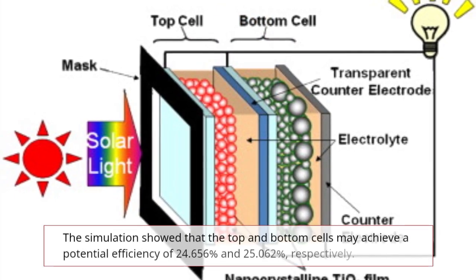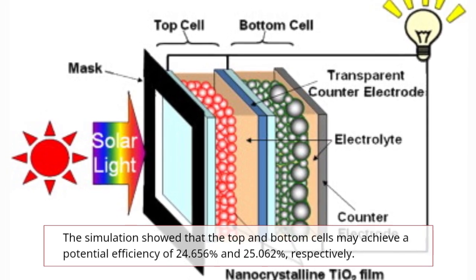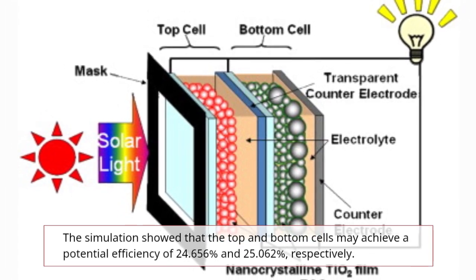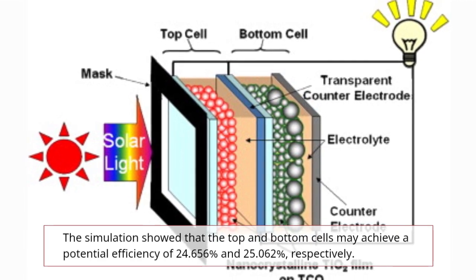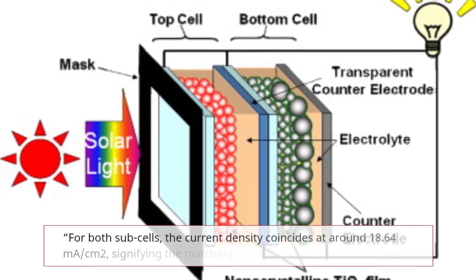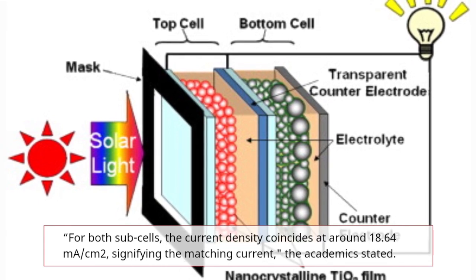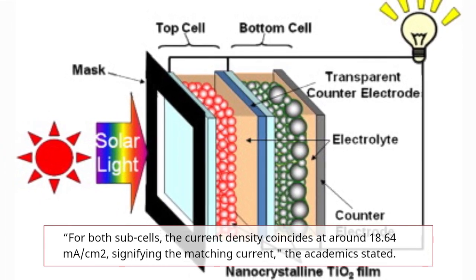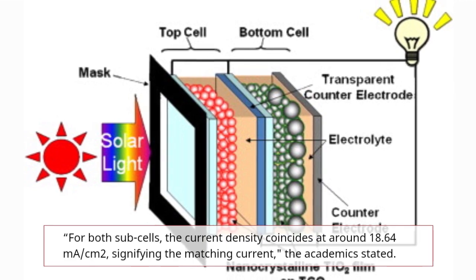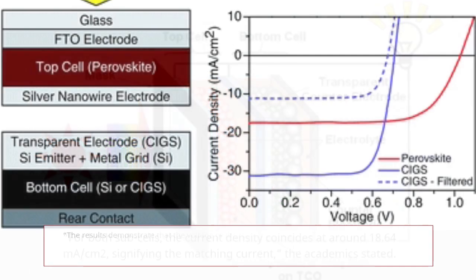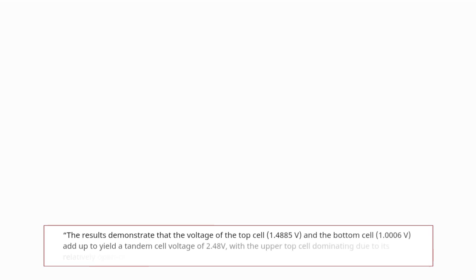The simulation showed that the top and bottom cells may achieve a potential efficiency of 24.656% and 25.062%, respectively. For both subcells, the current density coincides at around 18.64 mA/cm2, signifying the matching current, the academics stated. The results demonstrate that the voltage of the top cell, 1.4885 V, and the bottom cell, 1.0006 V, add up to yield a tandem cell voltage of 2.48 volts, with the top cell dominating due to its relatively large open circuit voltage.